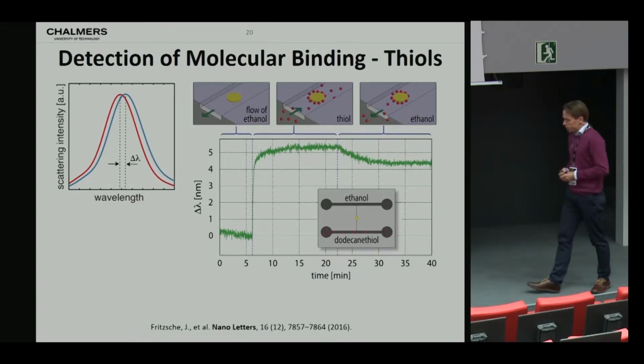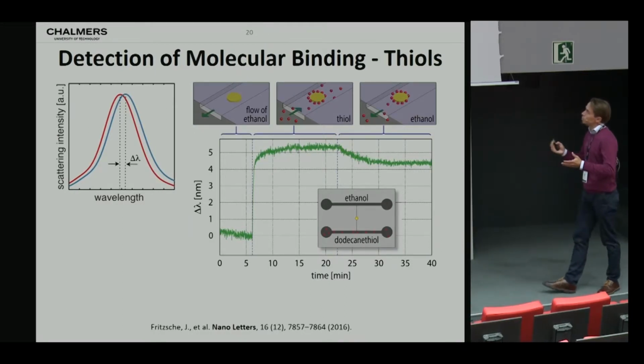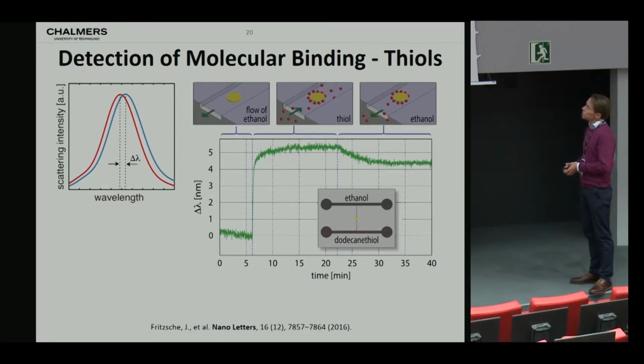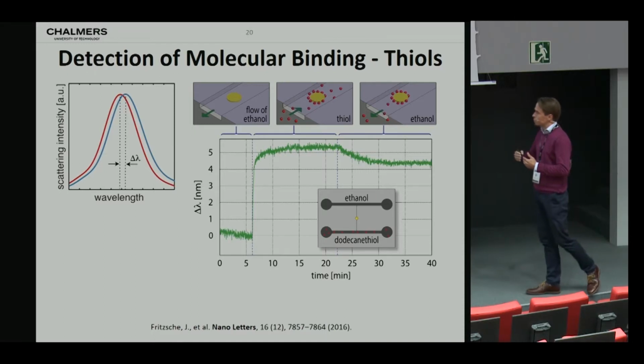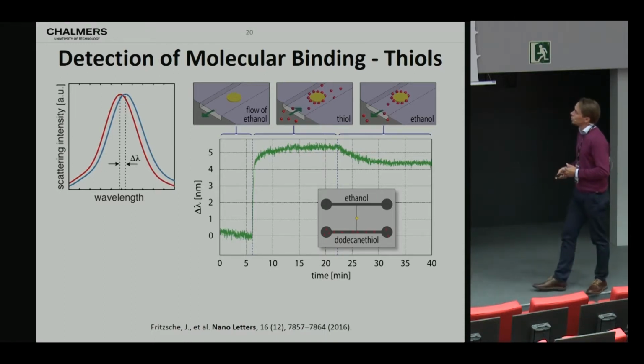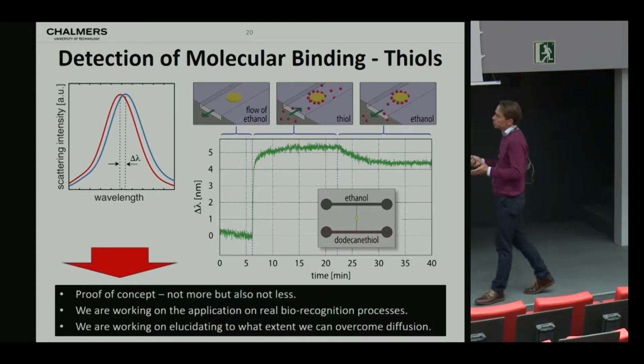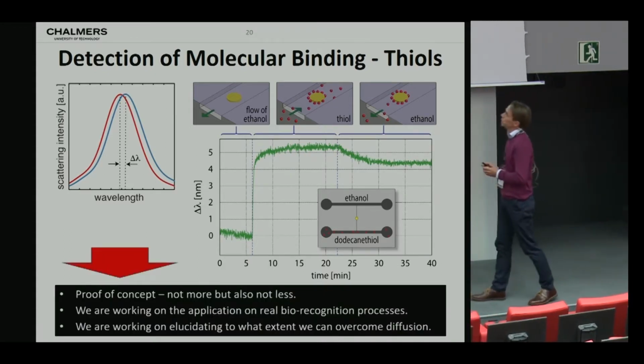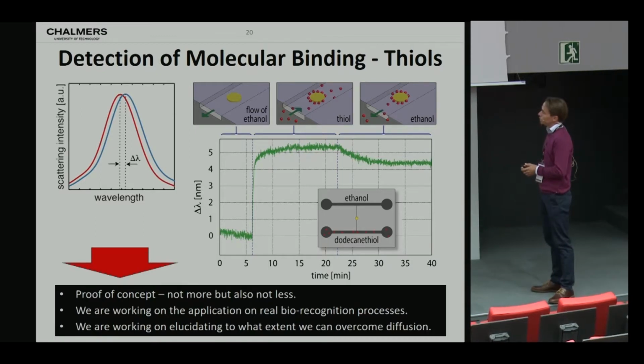This is what we have done in the next step in a very simple proof of principle type experiment where we expose a single nanoparticle, a gold disc in a nanochannel, to a thiol solution, and indeed we are able to detect the binding kinetics, which is actually quite fast for being a thiol, which says something about the mass transport aspect of the whole thing. But other than that, for the moment, let's just say this is a proof of concept that we can detect molecular binding to the nanoparticle.